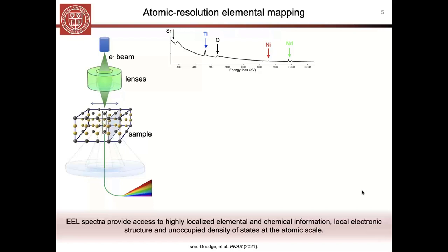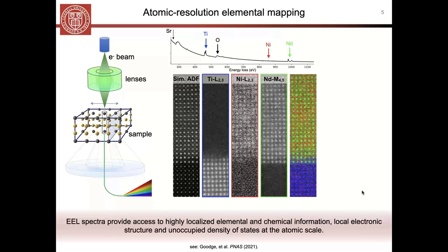In this case, you can see the different elements in the sample that I've labeled here. Using those edges, one of the very common things that you'll see is elemental mapping. And of course, we can do this with atomic resolution. So again, for these really precisely engineered materials that I study, understanding exactly the atomic structure of an interface, for instance, which we can study with this EELS map down here, is really important for the work that we do.